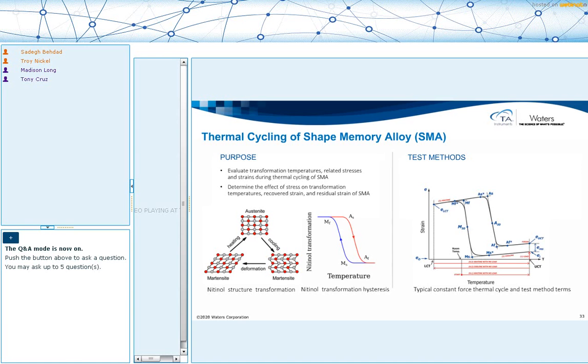Now we are heating back up. We start heating back up. In the beginning, it's linear because it's just a normal material, no phase transformation, until we start to form austenite. Then as you're increasing temperature, instead of expanding, your sample length is decreasing now. And then we go back to your upper conditioning temperature, and we measure the final strain at your upper conditioning temperature, and we look at the difference of the two as a residual strain.